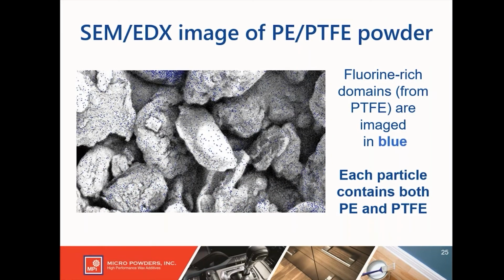So here is an SEM EDX image. This is a polyethylene PTFE composite powder. So you see the large gray domains, those are the wax particles. You see the blue dots, that is fluorine being sensed from the PTFE by the EDX. So you can see that each particle contains both polyethylene and PTFE. And in the case of our product, since it's melted before it's made into this particle, the polyethylene is throughout the particle. It's not just on the surface of the particle. So if you wear away that particle, you continue to expose both polyethylene and PTFE.